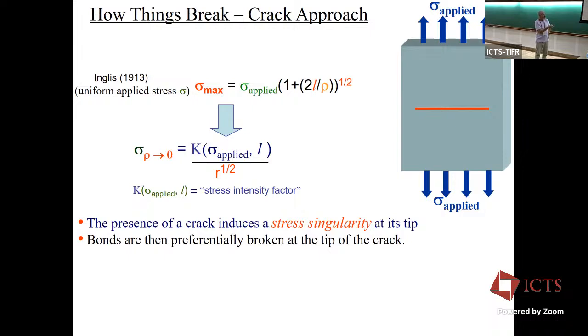In fact, they go as some factor K, which the experts call the stress intensity factor, divided by the distance R from the tip of the crack to the 1/2 power. So as R goes to 0, the stresses at the tip of the crack become singular. So this is the reason that things break at much less stress than one would naively calculate. And the reason is that this is an honest to God real world singularity. And anytime you have a defect in a material, a crack, you're going to get that singularity at its tip.